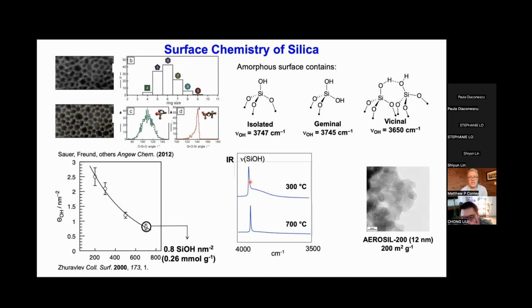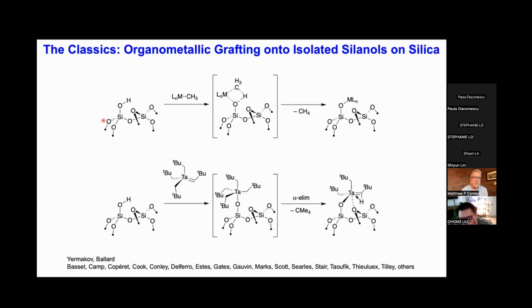And so what we see, if we take silica dehydroxylated at a lower temperature, we see this broad bump that's reflective of these vicinal silanols. We heat to higher temperatures, that collapses because we're basically eliminating water and regenerating siloxane bridges, okay? How these interact with organometallics is dependent on the type of compound that you throw at it.